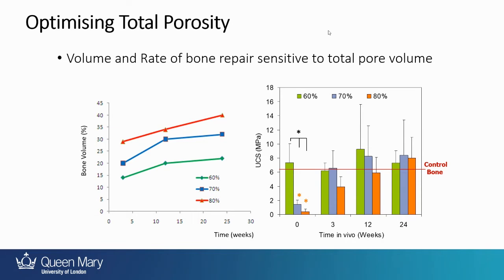And then if you do mechanical testing of the grafts after they've had bone incorporated in them, you can see that this red line indicates the strength of control bone in the area we put the implants in. And you can see that even though you've got very different mechanical properties in your starting implants, by the end of 24 weeks, everything's statistically the same, because the bone knows what strength it needs to be. Now it needs to be the strength of surrounding control bone, and that's controlled the rate and the volume of bone that's regenerated in those grafts.